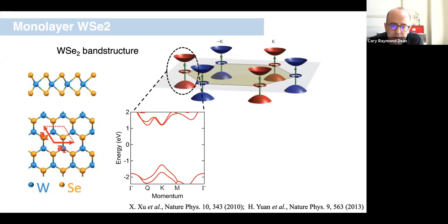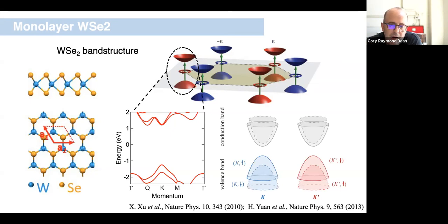And this gives rise to a band structure that has a band degeneracy, but not really. One of the interesting things about this band structure is that there ends up being a locking of valley and spin ordering in the system. And within each valley, there ends up being a splitting of the spin ordering due to spin-orbit coupling. So altogether, that gives rise to a scenario where we have K up and K prime down as the two degenerate energy bands. And those are energy separated from the lower spin K and the upper spin K prime bands, et cetera.